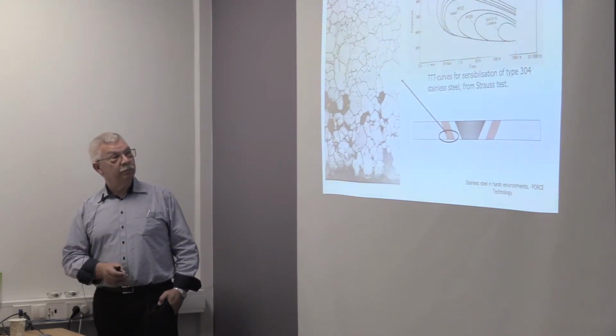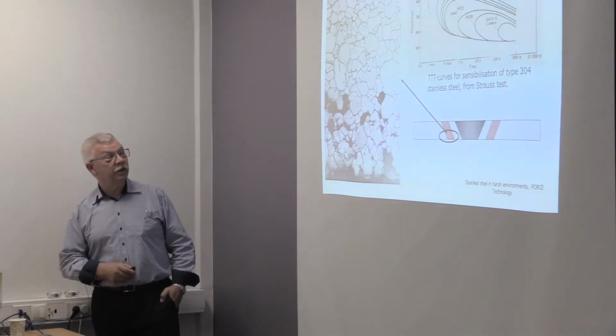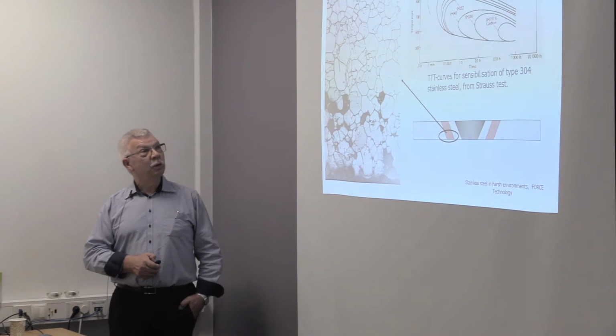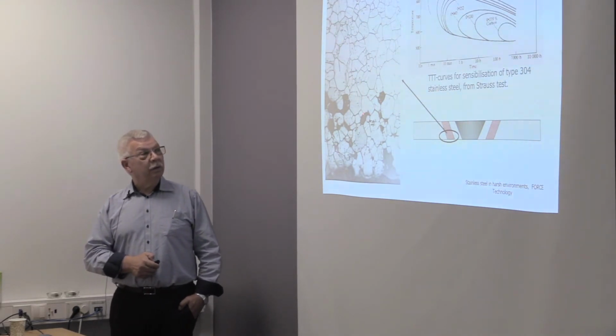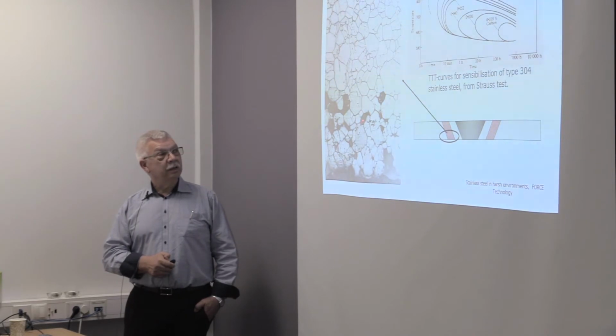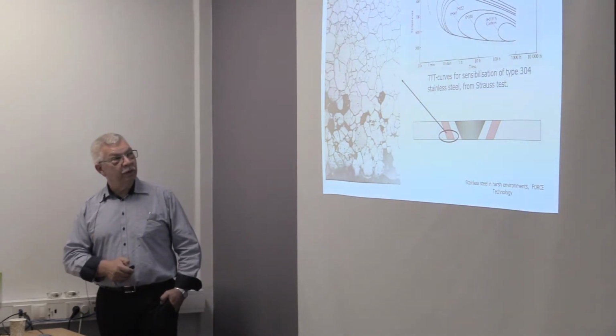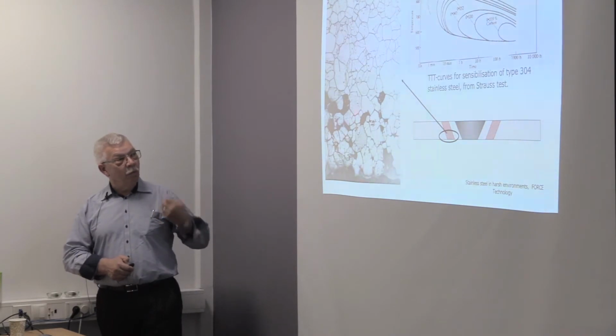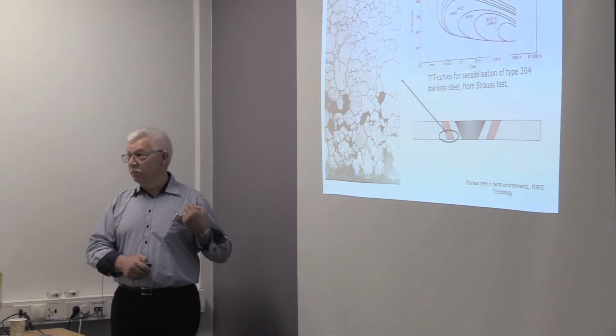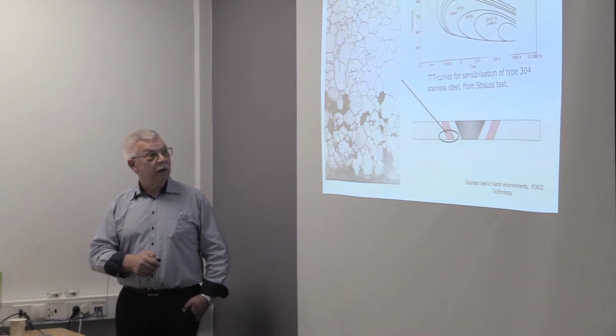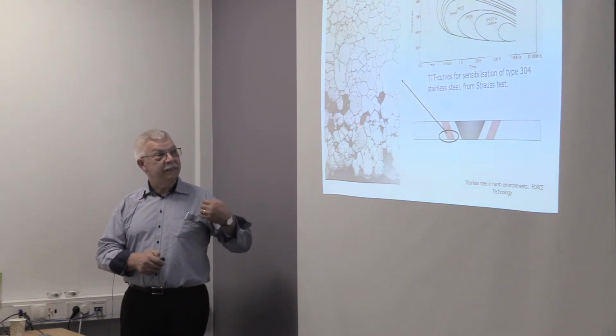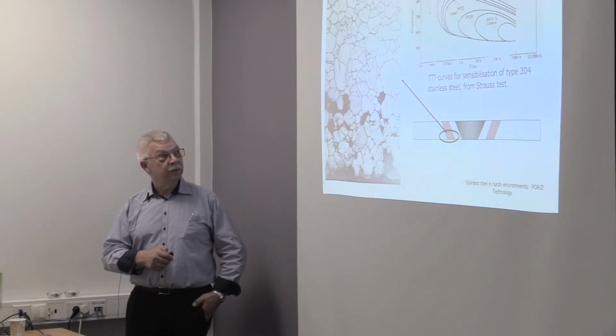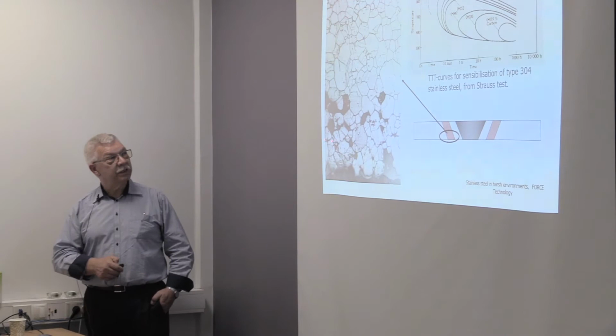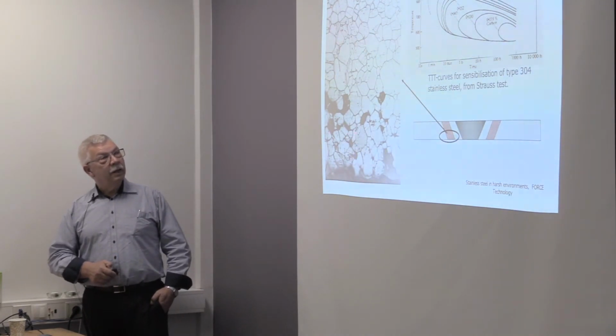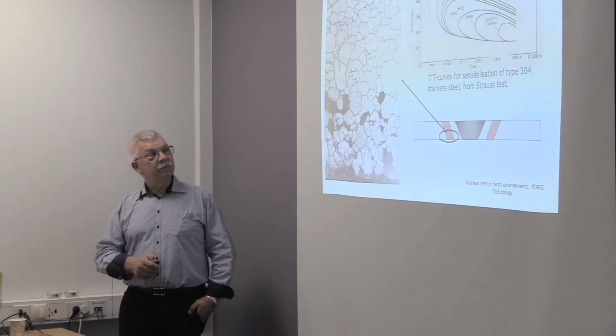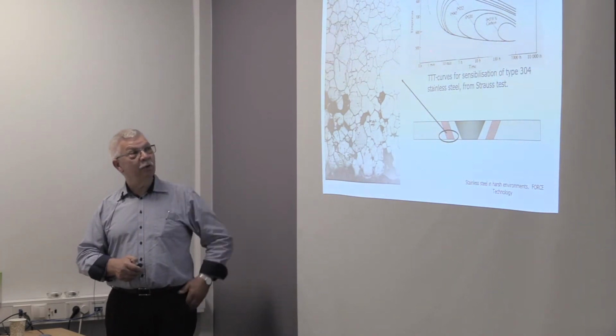This is a traditional welding problem in stainless steel. Too much carbon in the steel will cause trouble with sensitized material. The carbon would be on the grain boundaries, forming carbides with the chromium, and around these chromium carbide particles, chromium will be depleted, and we will have corrosion which makes the material fall apart like sand grains, as you see here.